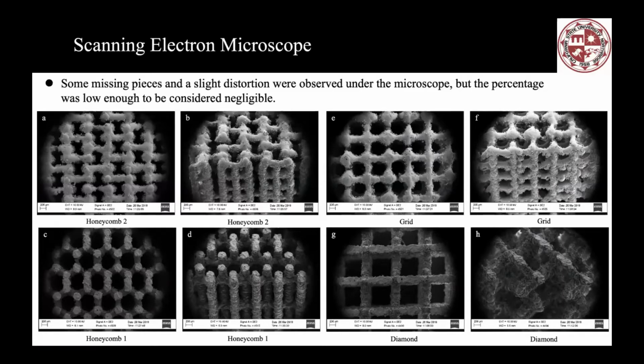So the high energy laser will melt or sinter the metal powder and then combine them together. Here inside of the metal powder, you can see it's not a perfect shape, either in the rectangle or in the circle, even though we designed that in that shape. But this is for the bone structure, so I think this is fine. But for mechanical parts, we have to make sure they have a really good finish surface. But this is for the bone, because eventually the cells will grow inside of the scaffold, and the rough surface will help the cells to grow as well.